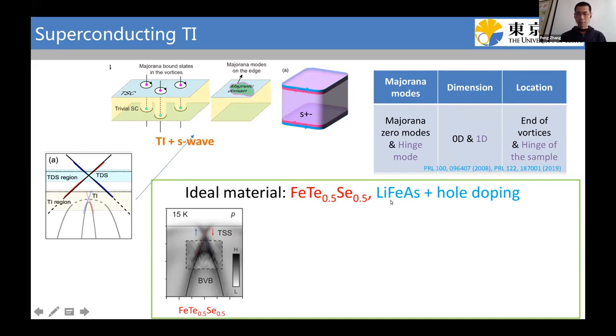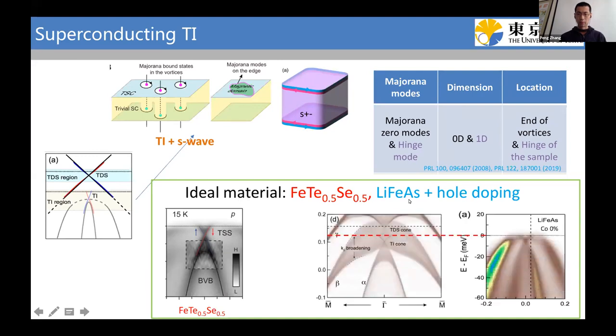For the parent lithium iron arsenide, it's not a very good candidate because in the experiment it was found that the Fermi level lies in between the two Dirac cones. It does not cross any of them. So if we want to study this topological insulator plus S-wave case, we need to shift the Fermi level down to cross the surface Dirac cone.